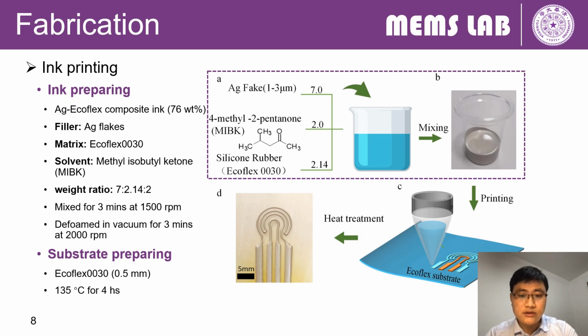Methyl isobutyl ketone solvent is used as a dispersion agent here. It helps to reduce the thickness of the ink for easy printing and prevent the curing of Ecoflex at room temperature. The sensor's substrate is also prepared in advance using Ecoflex.